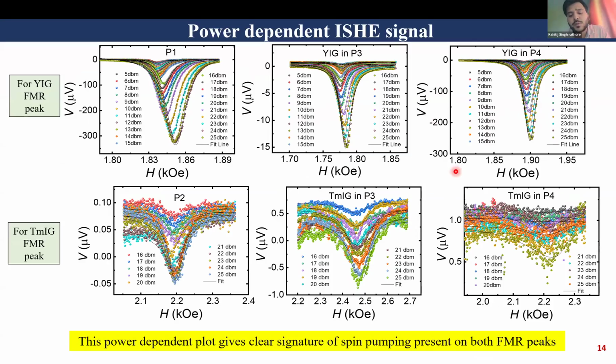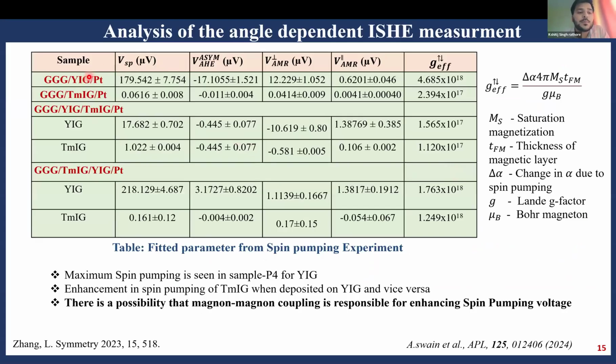So this confirms the presence of spin pumping in our samples. With the corresponding spin pumping voltage, in the case of the YIG sample, VSP was found to be around 180 microvolt for the single layer YIG. But when this single layer YIG was compared with the bilayer sample, with TMIG at the bottom and YIG on top, the signal value increased up to 220 microvolt. Similarly, for the TMIG single layer sample, there was almost zero microvolt of signal, but when it was placed on top of the YIG, it was around 1 microvolt. Such an increase in the spin pumping signal led to some of the physics behind this. So we attributed this to an interfacial exchange coupling present in our system.